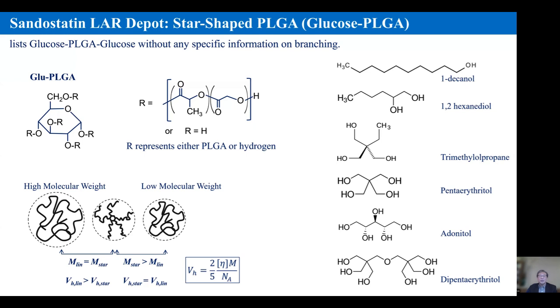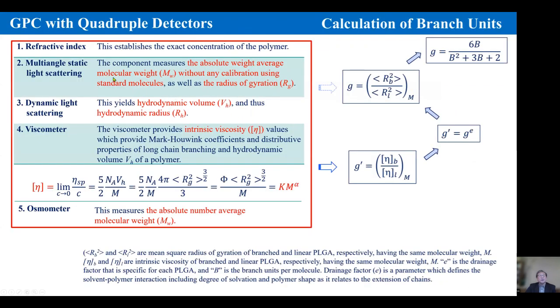So the difficulty was that, most of the time, if you look at the right side, with different initiators having different hydroxyl groups, you can actually see how many branches are there based on NMR. But somehow with glucose PLGA, the glucose initiator does not show any peaks in NMR analysis at all. And that was the problem in the beginning because we thought that there were no PLGA chains attached to glucose at all, but that was not the case. By using carbon-13 NMR, etc., with carbon-13 glucose, there are glucose PLGA. So we had to figure out exactly how to characterize glucose PLGA. The way we used was using GPC.